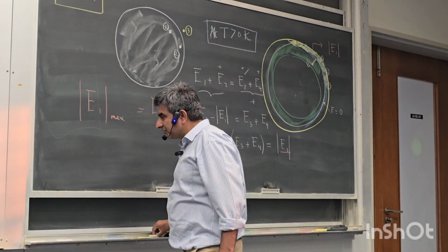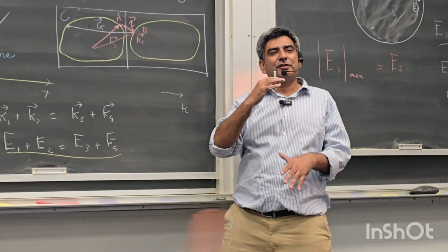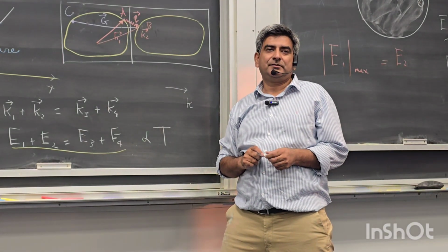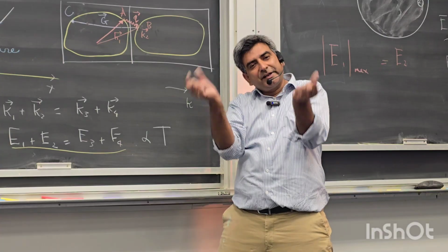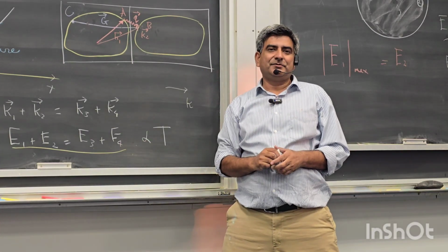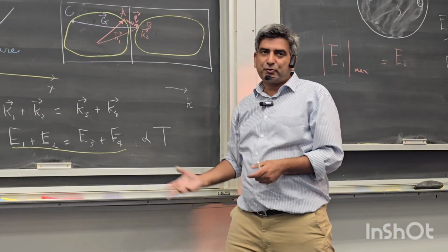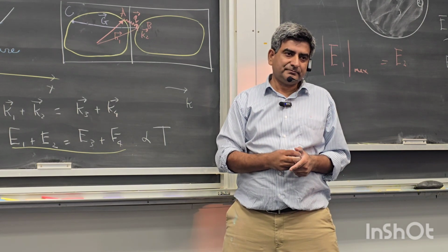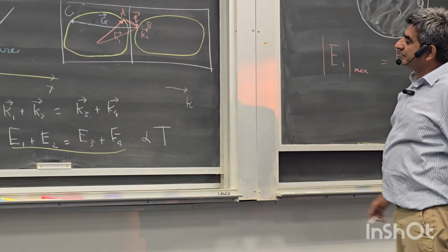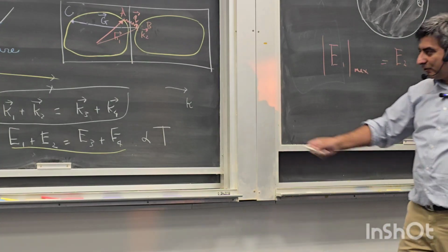So this constraint gives a temperature dependence on two electron scattering, which is of the order of T. So everything lies within this narrow range of width kBT inside the energy diagram. So electron scattering does take place, and it looks like it's proportional to the temperature T. Okay, but what about this constraint? This is another constraint. We haven't considered this constraint.